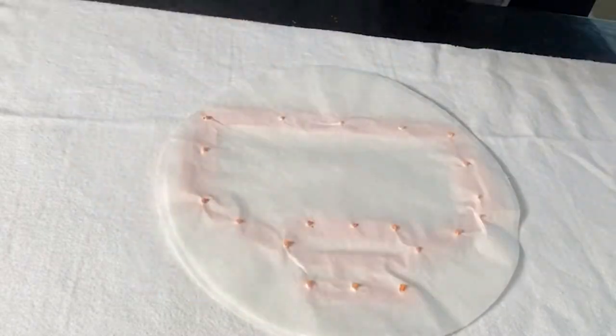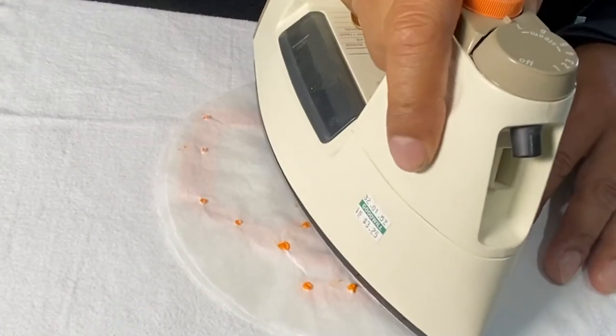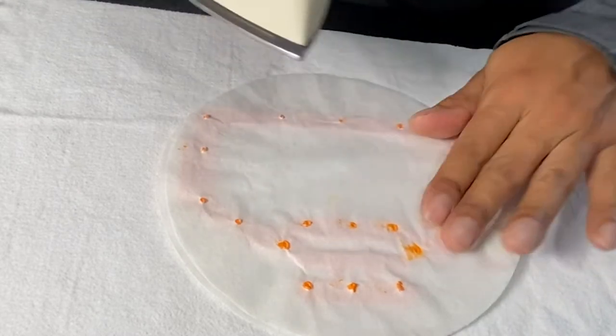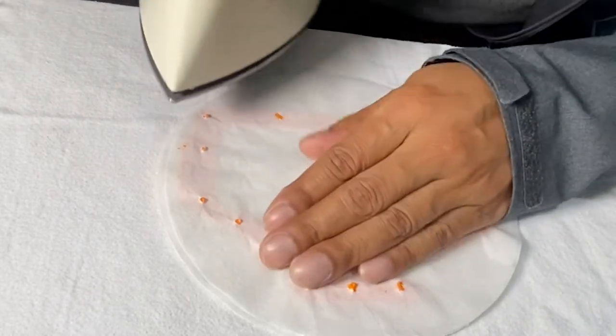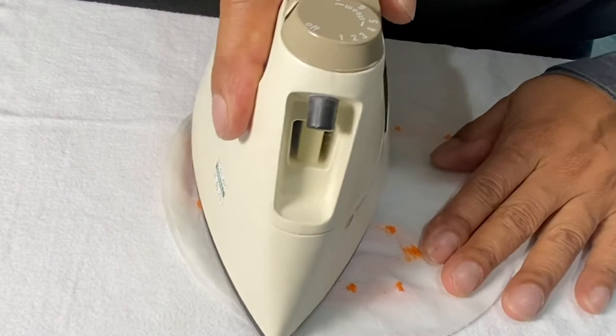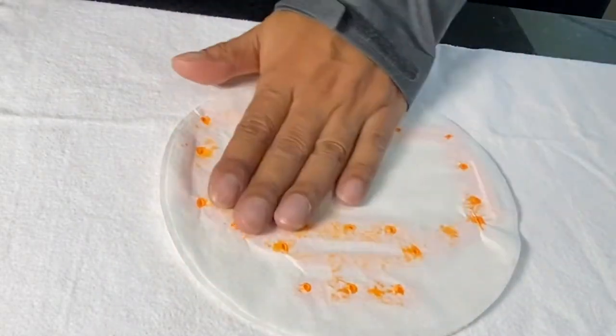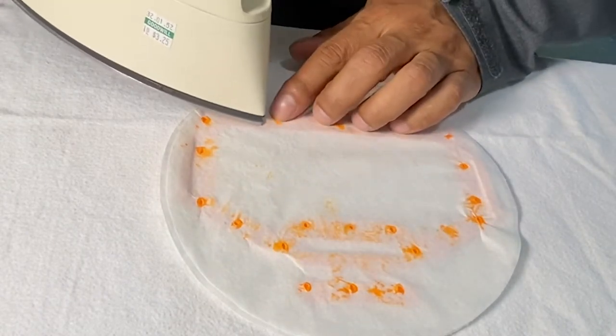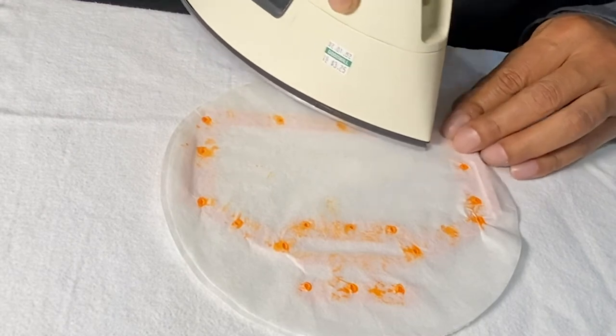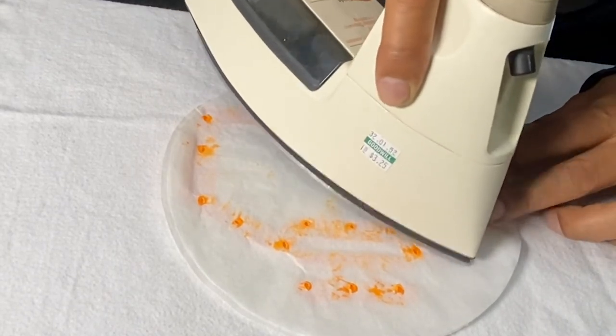Once you have it through, you have all three layers permeated. Now with a hot iron, just go ahead and flatten the PLA spurs — run it through so you can smear them. The first layer will make direct contact and it will be extreme adhesion. The second and third layers will use the barbs that we are flattening out with the hot iron right now. Sometimes the second layer will also adhere because the material becomes very malleable once heated to a high temperature.